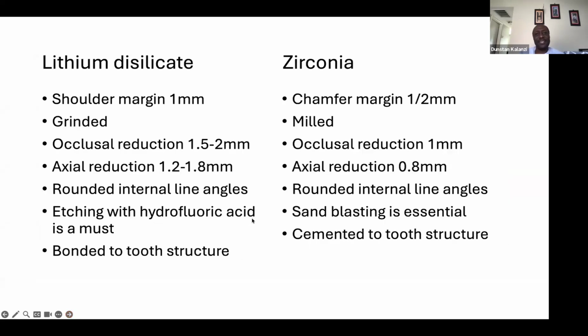So briefly, let us look at the difference when you're prepping, if you compare the glass ceramics to zirconia, what major differences are there? For your lithium disilicate, your shoulder margin is 1 millimeter. When you go to zirconia, you can even bring it down to 0.5 millimeter. Lithium disilicate can be ground, but can also be milled, but zirconia is basically milled. And that's just basically because of the material.